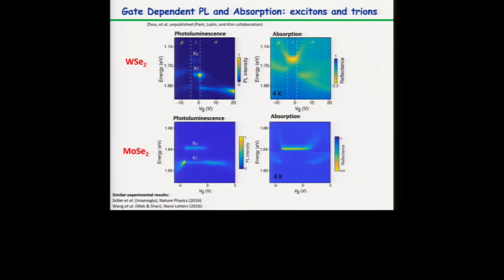In absorption, we also see this neutral exciton and the charged exciton, but they move in different directions. And the reason is it's usually blue shifting because of the Pauli exclusion principle, since in tungsten diselenide, the spin polarization for the lowest conduction band is different than the spin in the upper conduction band, compared to MoSe2. In MoSe2 it is the same. So usually in MoSe2 we see mostly a blue shift, compared to tungsten diselenide where you see either a blue shift or a red shift for the other side.